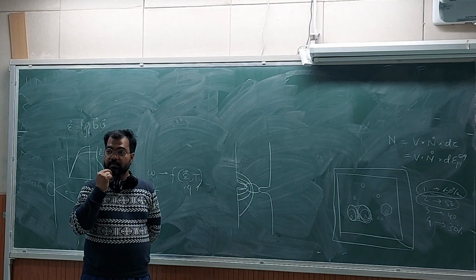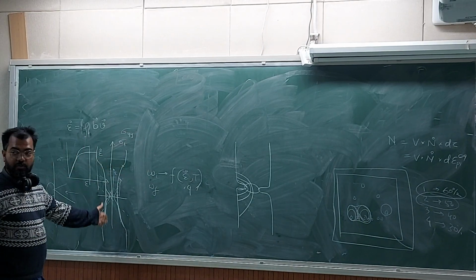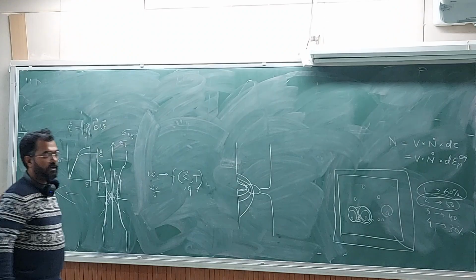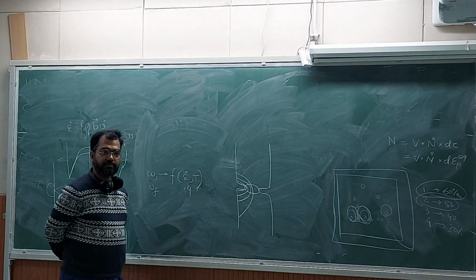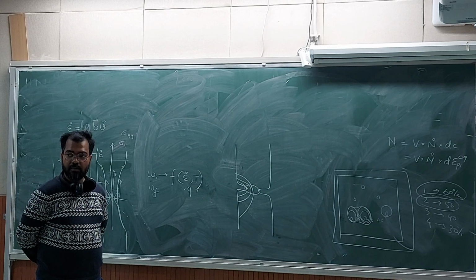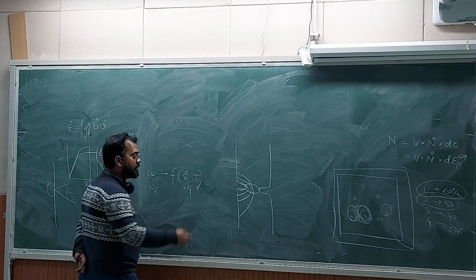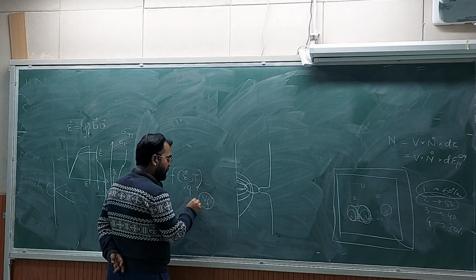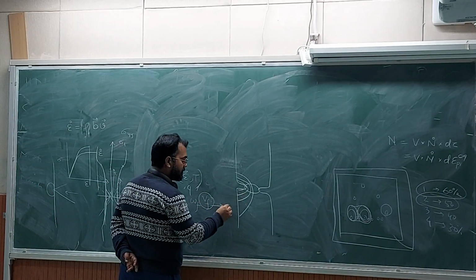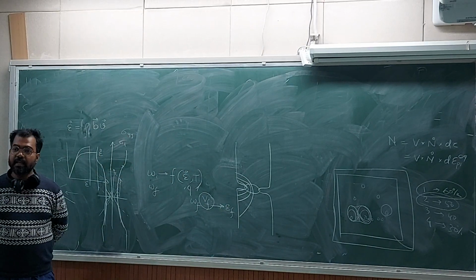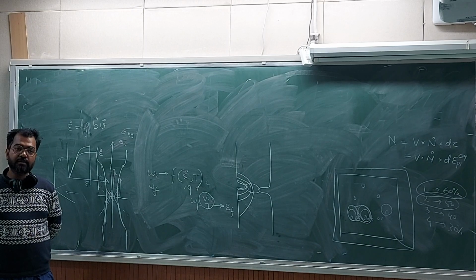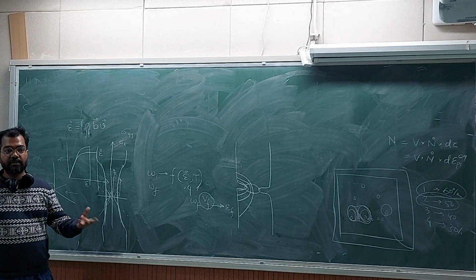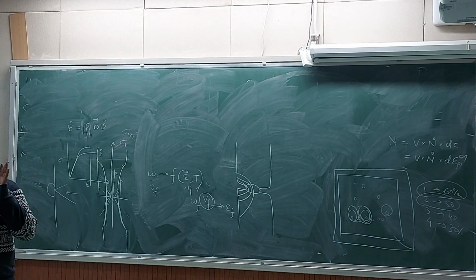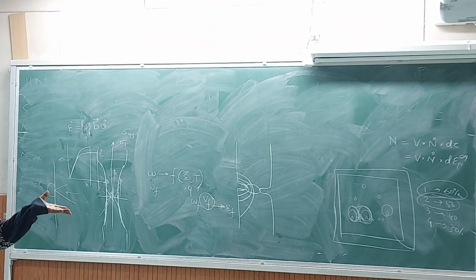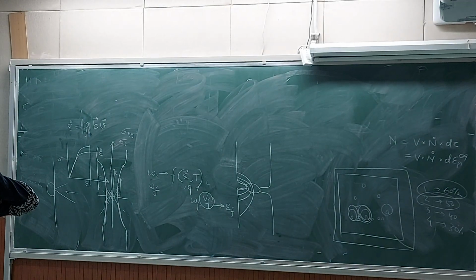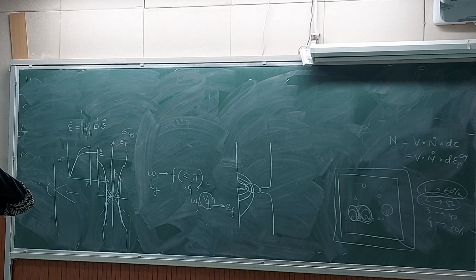But now the problem is that you can't get this variation too much. That you cannot get because this area is very small. You don't need to. Okay, you can just take the value of final void volume fraction, or omega F, for fracture strain, and then you calculate for different concentrations, so different constraint values, and then you have a relation of constraint with damage. The third thing would be to change it with temperature, and including all those, you can then put the information in finite element analysis, and then you can simulate the damage.